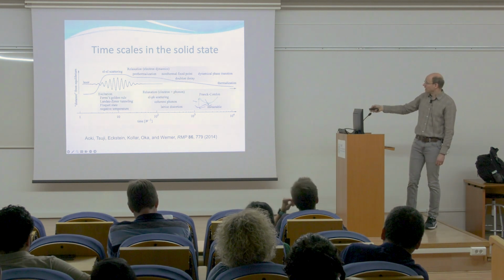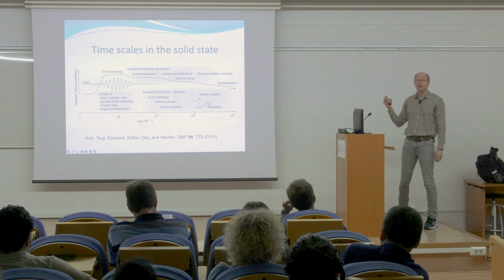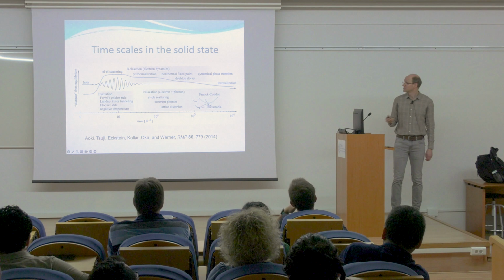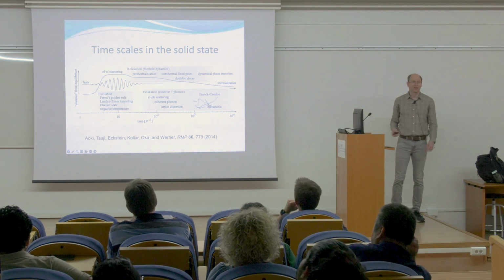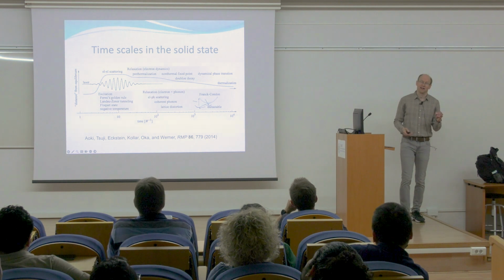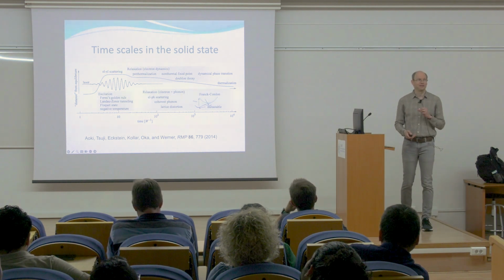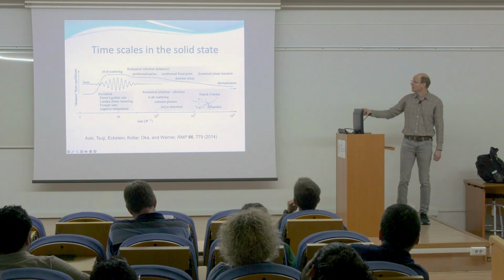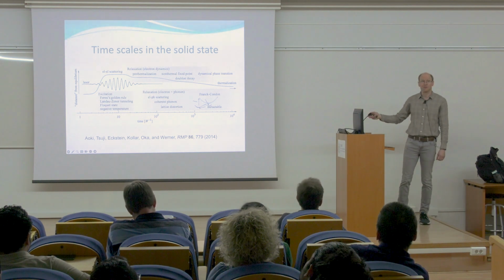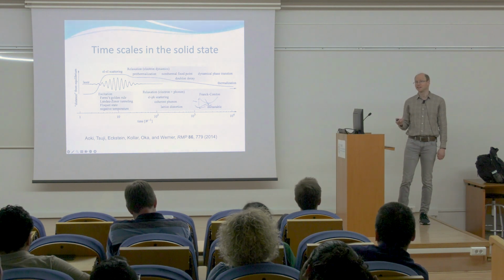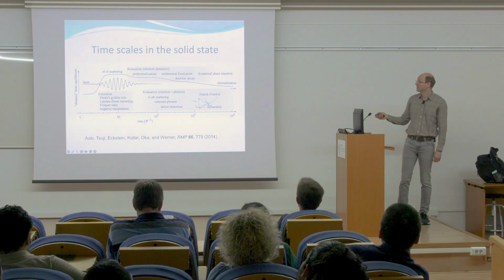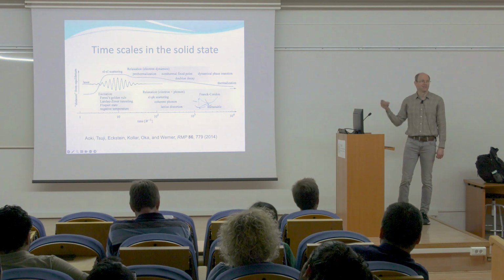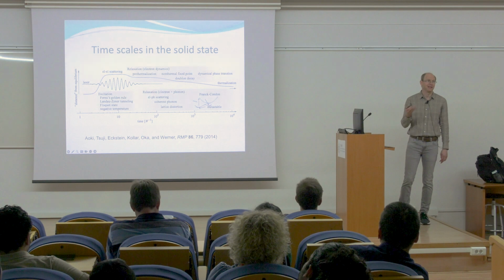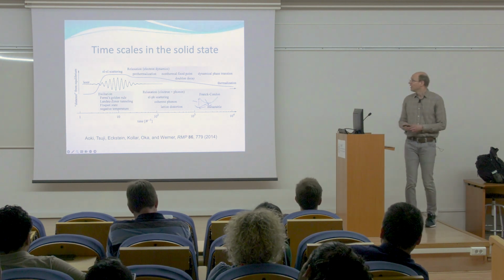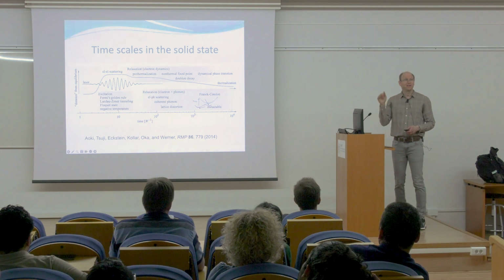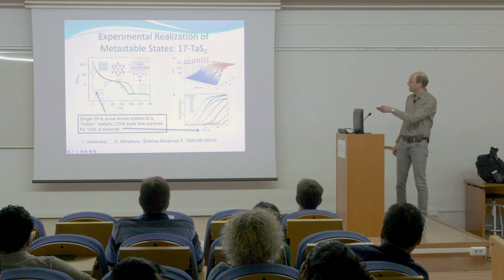When you shine a light on a material, the choice of the frequency you use is very important. I'll come to this issue especially near the end of the talk: you can choose the frequency in order to excite certain properties or certain degrees of freedom in the system selectively. If you use light around the electron volt range, you'll selectively excite the electrons. If you use light around the millielectron volt range, you'll selectively excite phonons, or maybe magnetic excitations, magnons. So you have selective targeting of your quantum degrees of freedom by how you choose the light.